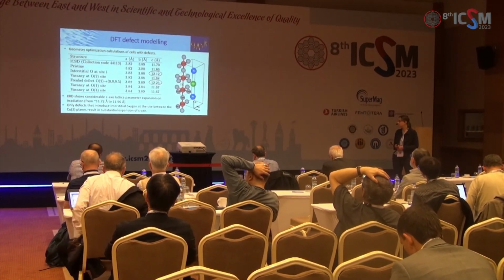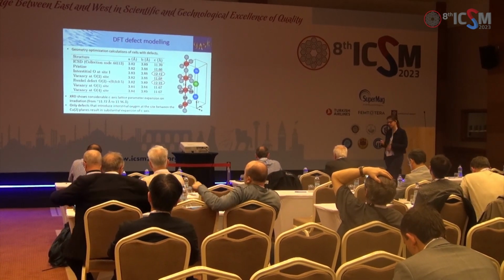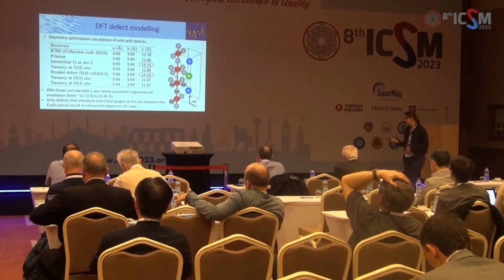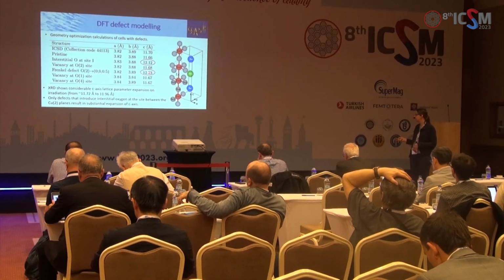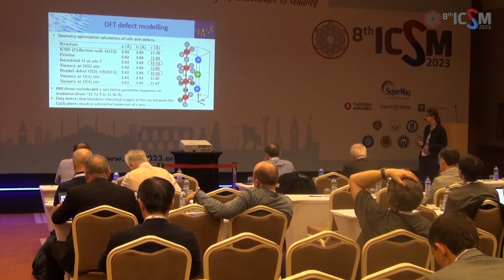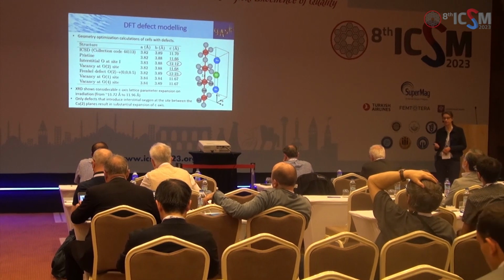So we particularly wanted to look at defects that cause that expansion in the C-axis when we do the modelling, which is what we see from defects that have this interstitial oxygen in this site here. So we're particularly interested in those ones.